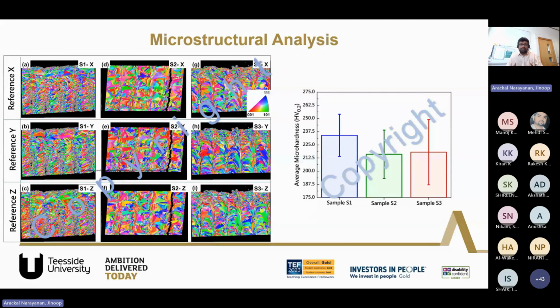And again, we got a very high hardness as compared to conventionally built Inconel 617 samples. But most of the samples had cracking, but we could avoid cracking in some of the conditions, which was not reported in this particular work.